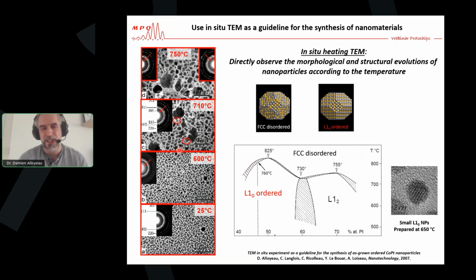The idea of my PhD at the beginning was to fabricate cobalt platinum nanoparticles in this chemically ordered L10 structure that you see here, because those nanoparticles have very interesting ferromagnetic properties that allow you to have a permanent magnet even when they are very small. So the idea was to fabricate small nanoparticles, below 3 nanometers, with this specific structure. And we used pulsed laser deposition, which is a vapor phase deposition technique, to obtain those nanoparticles. We use a laser to interact with pure metallic targets, and we do an alternating deposition of those metals on a substrate to fabricate those nanoparticles.